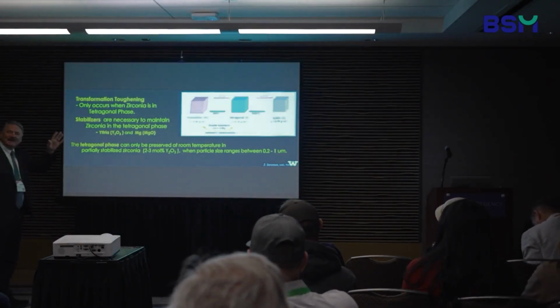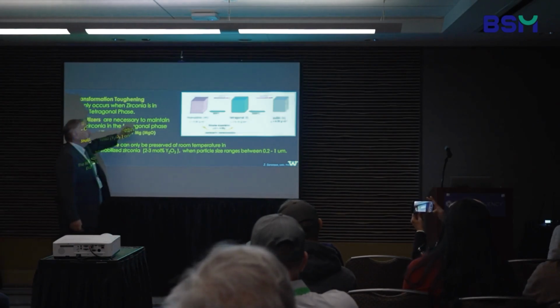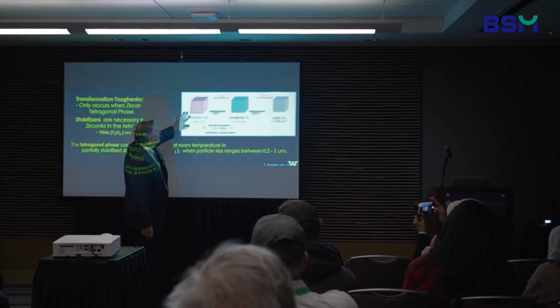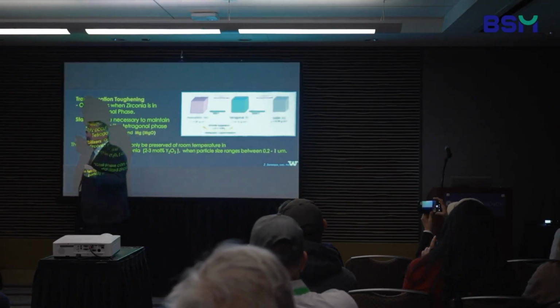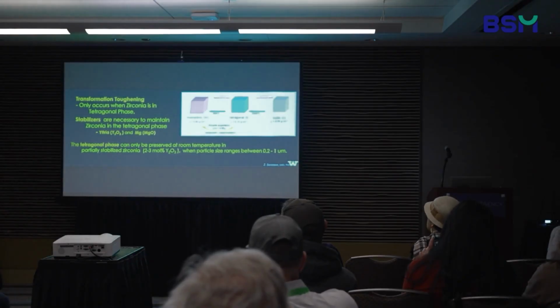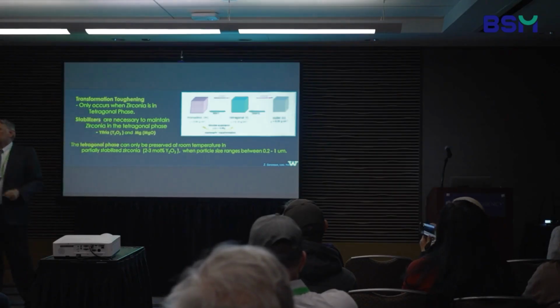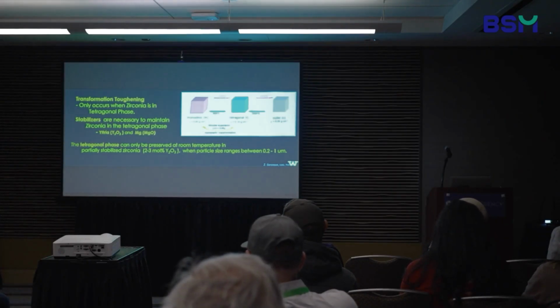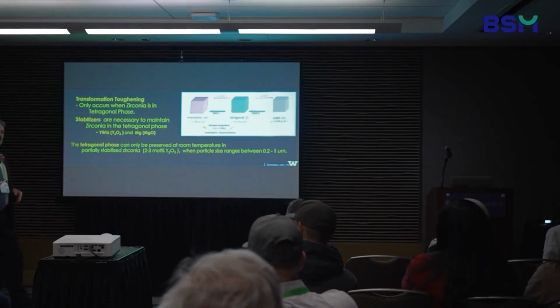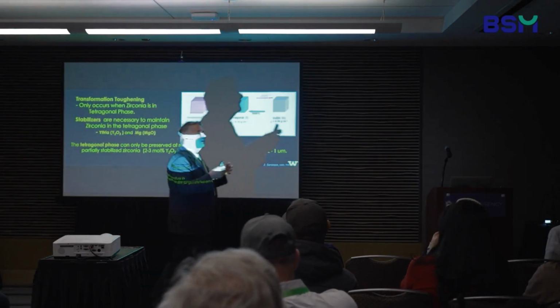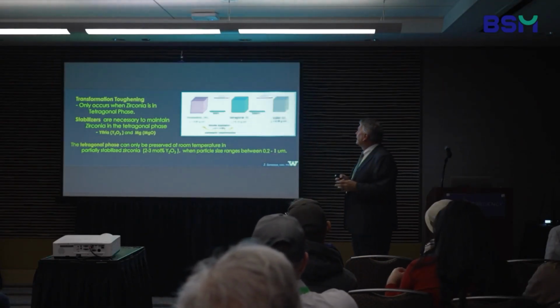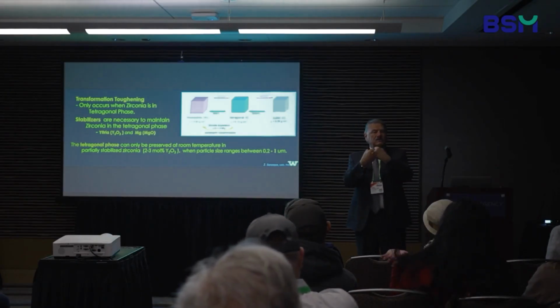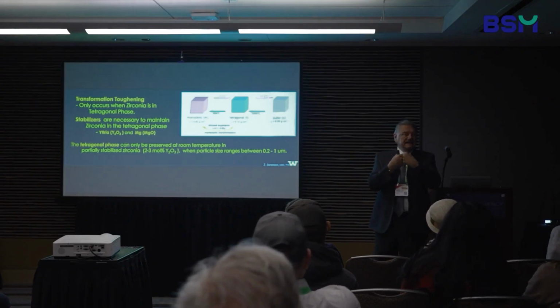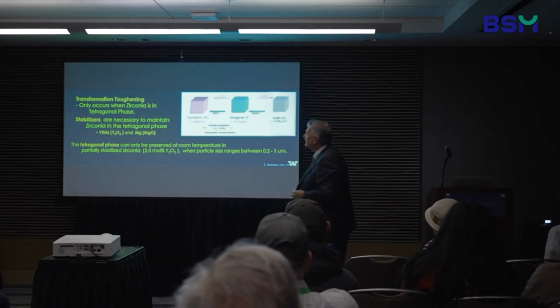And let's just go a little bit of science 101 here. So basically, the zirconia is normally in a monoclinic form, and we want it to be in the tetragonal form. And what they do is they add some yttria to that to stabilize it. And when you do that, then you have this amazing property in that it increases the fracture toughness of the material. It's called transformation toughening. And when you have the energy of a crack that's trying to go through that, it causes the expansion of the particles of somewhere between 3 and 5%, and that pressure of the expansion of those then closes off the crack and increases its fracture toughness. That's the resistance to the propagation of cracks.